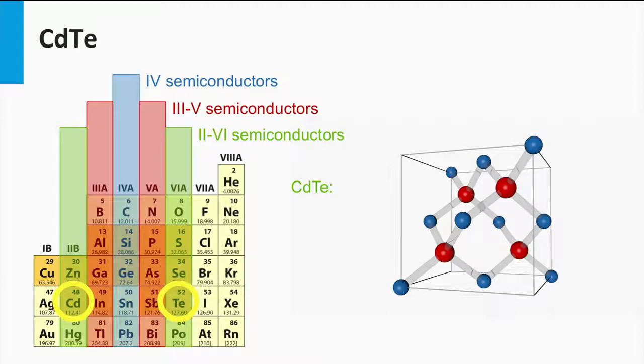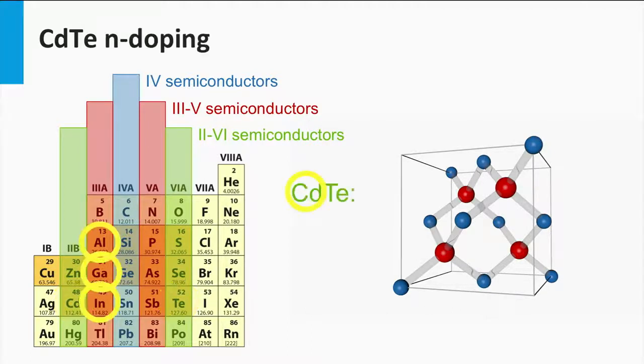Cadmium telluride has a direct band gap, consequently only a few microns of cadmium telluride is required to absorb all the photons with an energy higher than the band gap. It means that the diffusion length for the charge carriers has to be in the same order to have the light excited charge carriers collected at the contact.